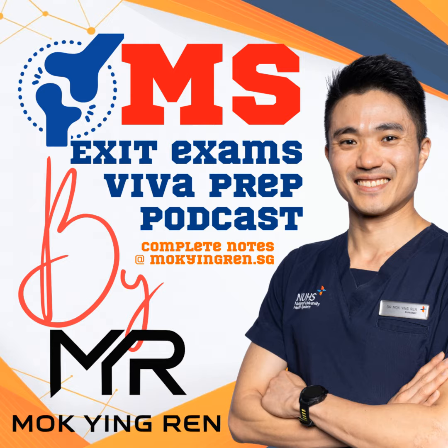What factors might increase the risk of XLPE failing in a knee replacement? That's a great question. There are several things to consider. One is the thickness of the PE. Thin PE, less than 8 millimeters, is more susceptible to failure, especially with XLPE. Another factor is the design of those articular surfaces. Flat or non-conforming surfaces can lead to higher contact stresses, increasing the risk of wear and fatigue. And of course, surgical factors like the alignment and positioning of the components also play a role.